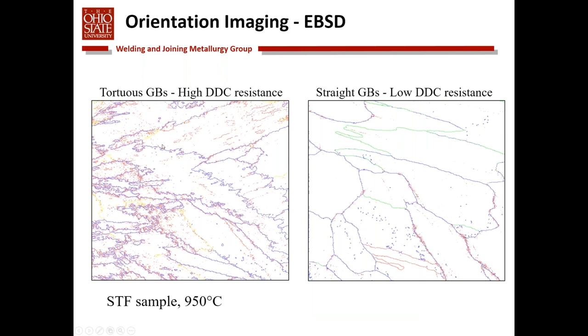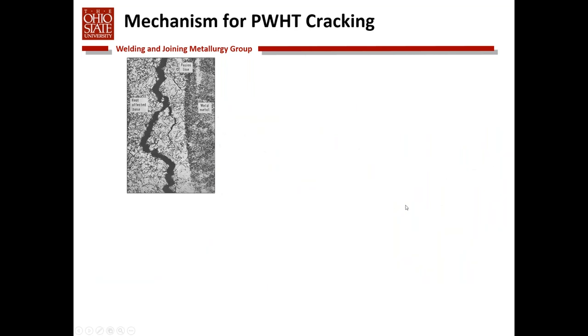This is another EBSD plot that basically shows a weld metal that has high DDC resistance, and you can see how tortuous, irregular these grain boundaries are versus a material with low resistance. In this case, if we apply a strain, sliding of these boundaries is quite easy. In this case, because of the tortuous boundary, those boundaries can't slide because they're basically locked together. And so it's a fairly simple, straightforward solution to the problem, simply adding alloying additions to cause precipitates to form at elevated temperature that results in these irregular grain boundaries.